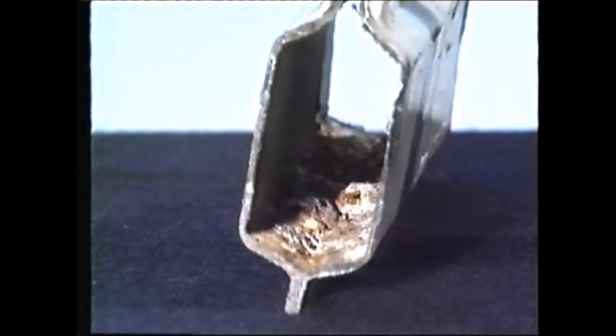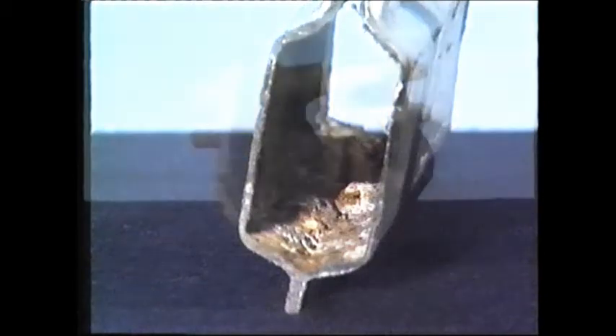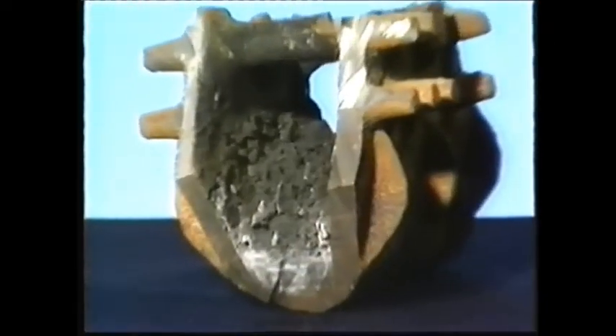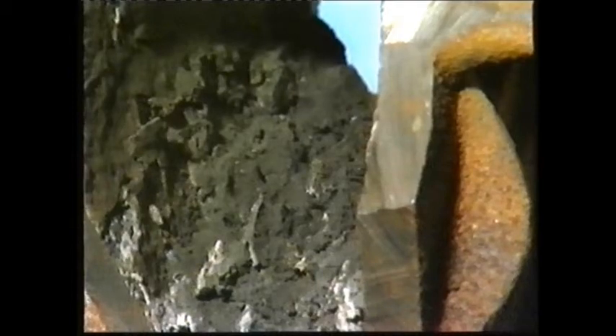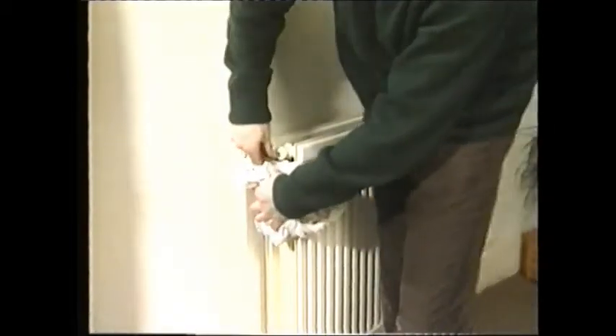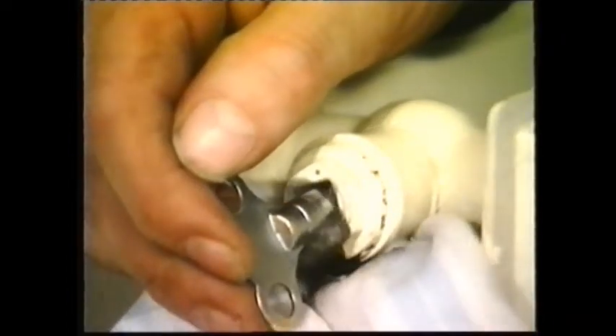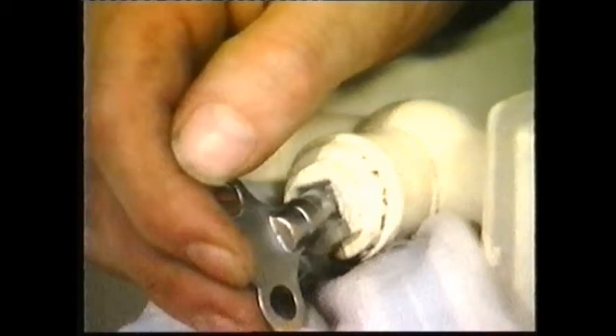Add to these secondary consequences the primary problem associated with corrosion, such as failed radiators which can pinhole within months or even weeks of installation, and the price of failing to treat the system becomes high indeed. High because the effects of corrosion can irreparably damage the reputation of both the equipment manufacturer and the heating engineer, and indeed the reputation of wet systems as a whole. And high because of the time spent carrying out repair or maintenance work under guarantee. Repairs that will need repeating unless remedial action is taken.